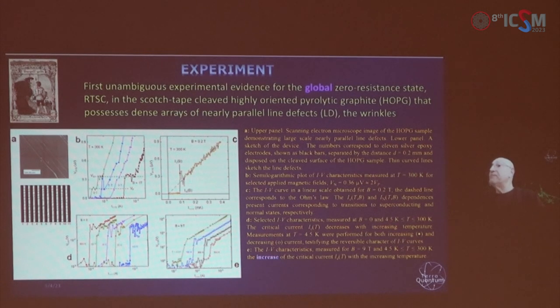actually changes and drops, as it is supposed to do, when we increase the applied magnetic field. This is just an exemplary IV curve showing the superconducting behavior pretty similar to what we see in usual superconductors, but in a graphite sample and at room temperatures, this global superconductivity which was never seen before.